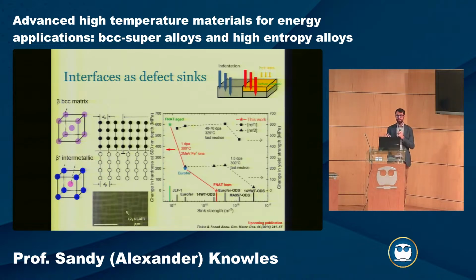So we've done some experiments looking at this. This was work at the University of Surrey where we did ion irradiation. You take a large accelerator, a large electric field, and then you can bombard ions into the surface of the material. Then we could do nanoindentation, a very small indentation method, and we can pick up the hardening from that ion irradiation.